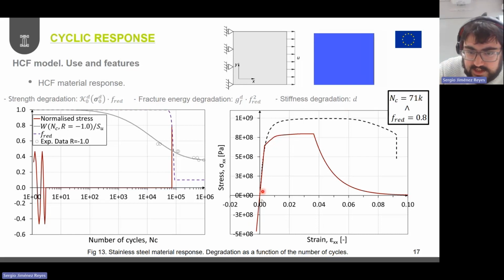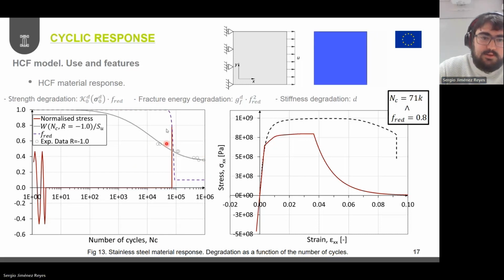So we have here first the cycles, and then we have the monotonic response of the material in terms of stress strain curve after applying 71,000 cycles. And this amount of cycles results in moving from fatigue reduction factor equal to 1 to fatigue reduction factor equal to 0.8. And this is basically a representation of the SN curve, the experimental data, and the fatigue reduction factor here is also plotted in this chart.